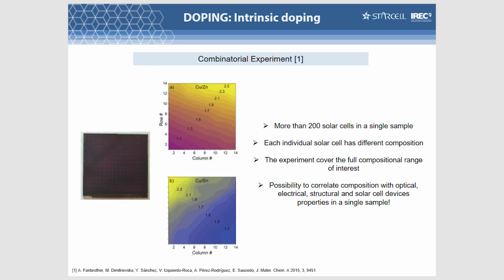And for studying this, in my group, some time ago, we started to perform an experiment with what we call a mega sample. It's just one sample, you can see here, 5 by 5 square centimeters, where all the interesting compositions are inside. So it's a graded compositional material. Then in just one sample, you can study all the compositions together. In this kind of sample, we can prepare more than 200 different solar cells, each of them with different composition. And of course, this experiment covers the full compositional range of interest. So we have access to all these types of kesterite together.